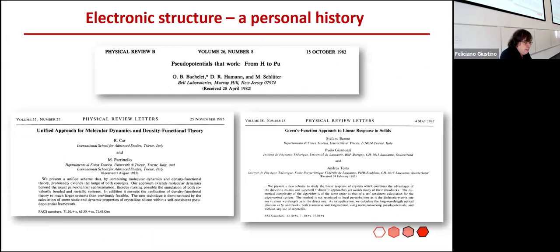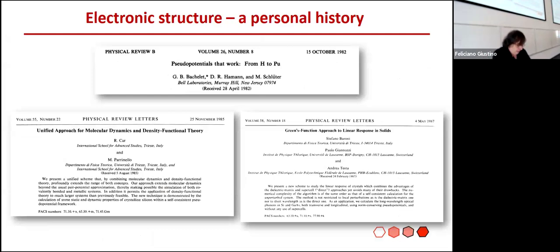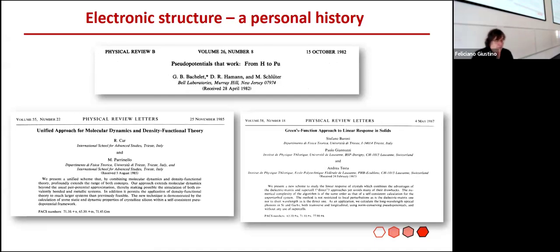Some of the key developments in the 1980s was the development by Hamann, Schlüter and Chiang of the idea of norm-conserving pseudopotentials that were transferable, representing well the scattering of electrons at various energies. Bachelet, Hamann and Schlüter developed pseudopotentials for the entire periodic table. So one could do materials calculations, one could do molecular dynamics with DFT forces thanks to the Car-Parrinello extended Lagrangian, and one could do perturbation theory with density functional perturbation theory. Applications to materials became present and common.